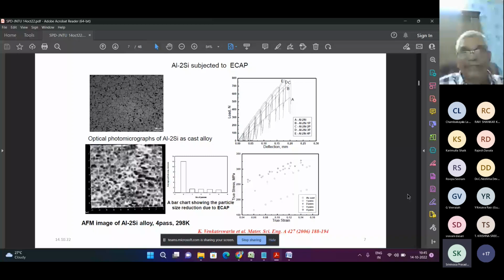You can see that the grain size has been drastically reduced, becoming an ultrafine grain size. And the silicon particles inside, in the center part, you can see how they are breaking. So there is a drastic difference between the initial stage and after one pass, two pass, three pass, four pass. With each pass we keep changing the direction of the sample, and you get different shapes and different sizes of silicon. This bar chart shows the silicon particle size reduction due to the ECAP process.